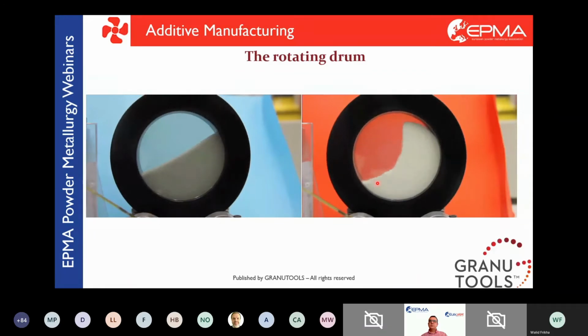So here you can see two videos. These are two drums rotating at the exact same speed. So the speed is the same. And on the left side, you can see a non-cohesive powder. So this means the particles are not sticking to each other. The cohesive forces are very low on the powder on the left. It's glass beads, for your information. On the right, the cohesion is higher. And so we can see that the flow is not as regular.